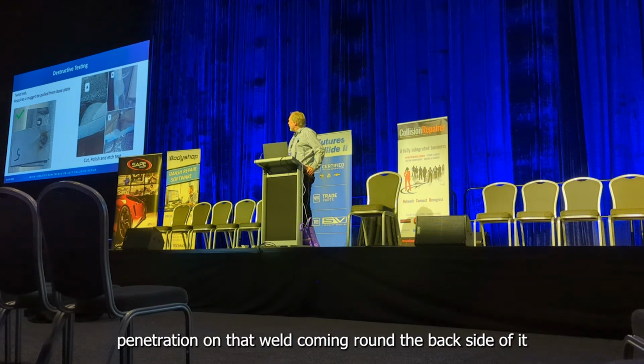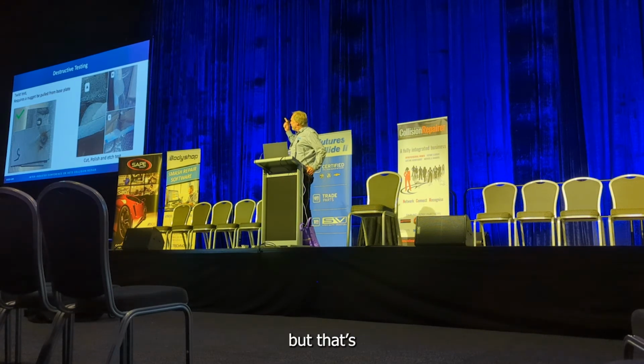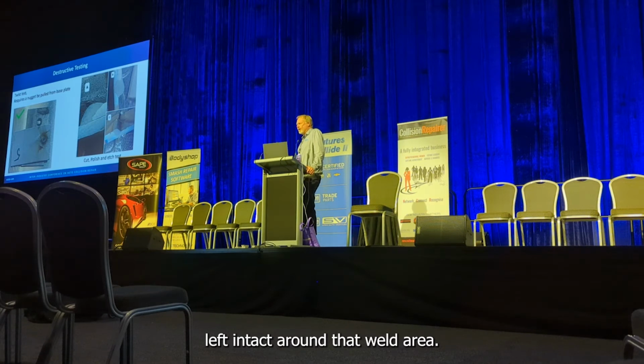Sample B, most people will really like the penetration on that weld coming out the back side of it, but that's where our fracture point is, along the edge of that weld. That's because there's no metallurgical structure left intact around that weld area. And sample C there, 30 to 50% burn into the base plate is what correct penetration is when we're welding.